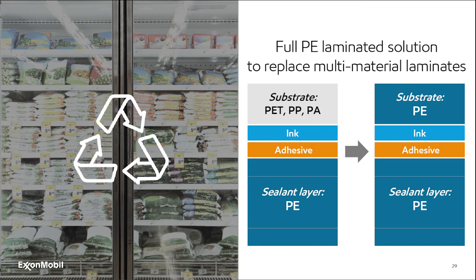But this is the laminate example. And you see the left-hand example here is the same as I had in my introduction page on the structures available. You see that the substrate can be PET, polypropylene, or polyamide. And in the case study shown by Amelie, you saw that all the examples except 4 were actually based on PET, polypropylene, or polyamide substrate. So what happens when you put these types of film into mechanical recycling? It will deteriorate the quality of the recycled pellets that come out. And the simple reason for that is that these polymers are not compatible with polyethylene, especially not PET and polyamide. Polypropylene can be compatible in a certain percentage, but it should be very low. So a design for recycling example would be to replace the PET, polypropylene, or polyamide substrate with a polyethylene substrate.